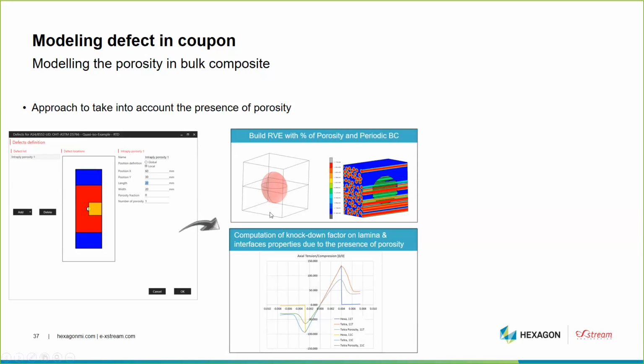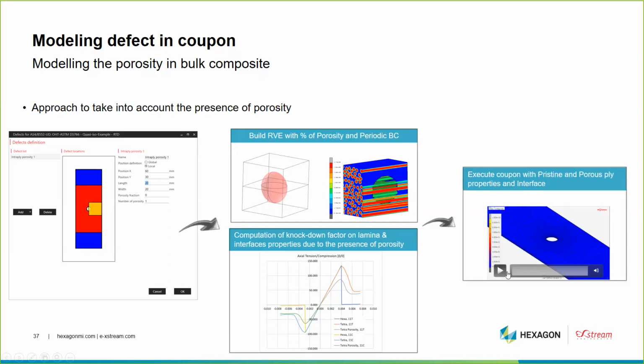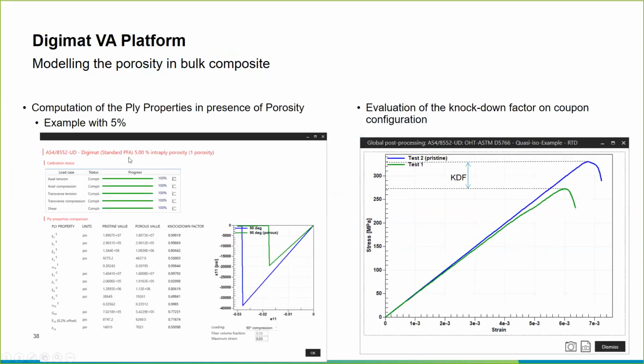So when we run this coupon, we will have two materials: the pristine material in the red part, and another material under the orange part, with the new property taking into account the porosity. Then we can run the coupon with the two types of material and compare the pristine coupon and the coupon with porosity. Typically, this is a result that we have for the ply when we have introduced 5% of porosity. This is the first step of the workflow: first, the ply property in the presence of porosity, and then we solve the coupon, the pristine coupon without porosity and the coupon with the porosity, and again we identify the knockdown factor.